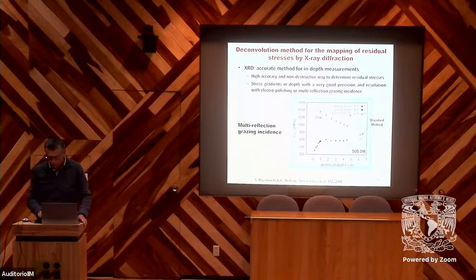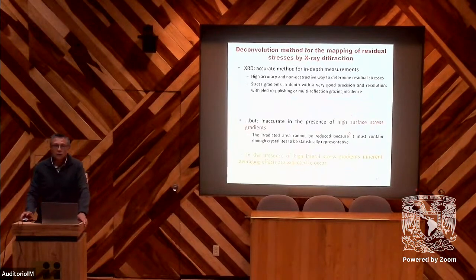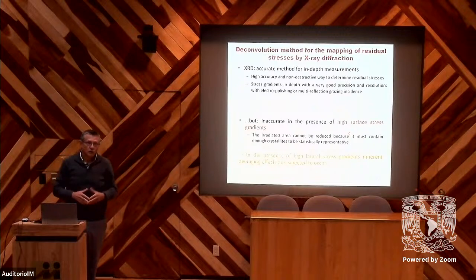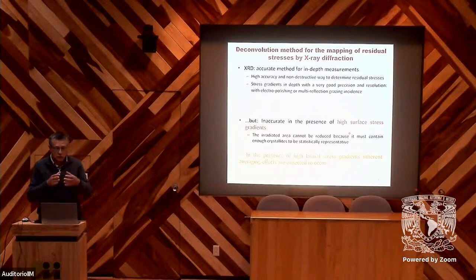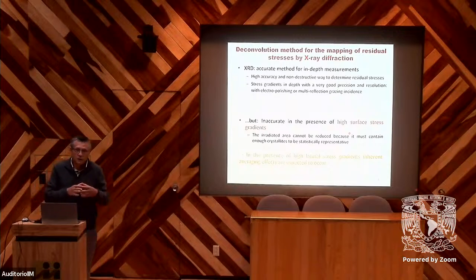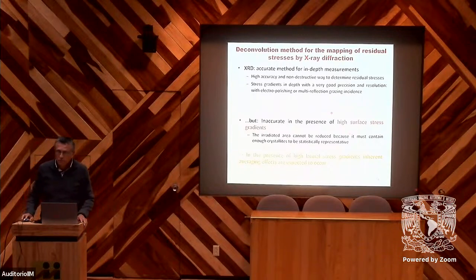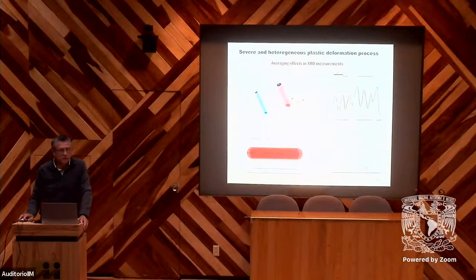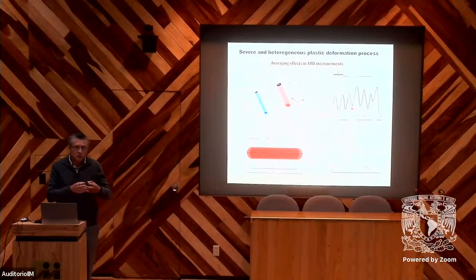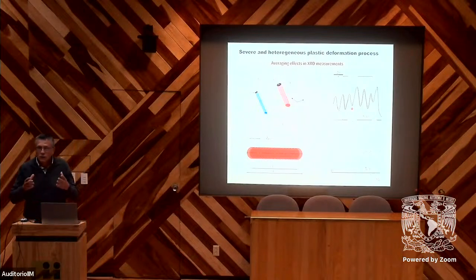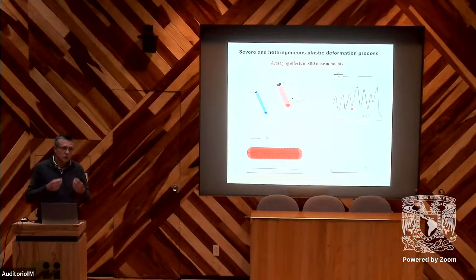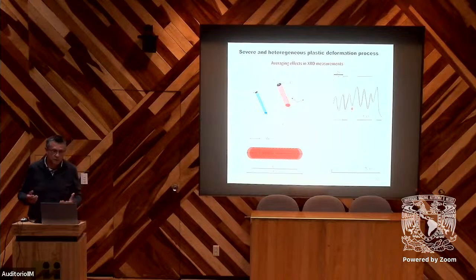But the problem is, if we have a surface gradient, we have a very poor resolution because we have a relatively big size of the beam. So we can, of course, reduce the size of the beam, but we always have some averaging. We cannot reduce it too much because if we reduce it, we will have only a few grains. That means we will need a very, very fine microstructure. So there are some limits.